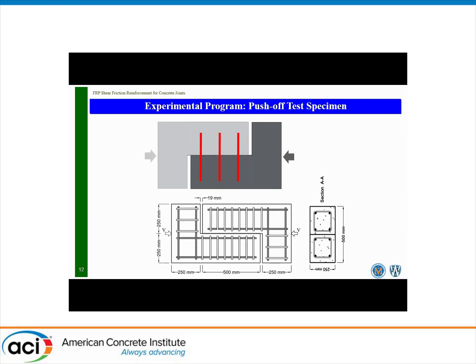The specimen consisted of two halves, two L-shaped specimens, cast at different times. For example, you start by casting the first half where the shear reinforcement is oriented, and after curing, you cast the second half.